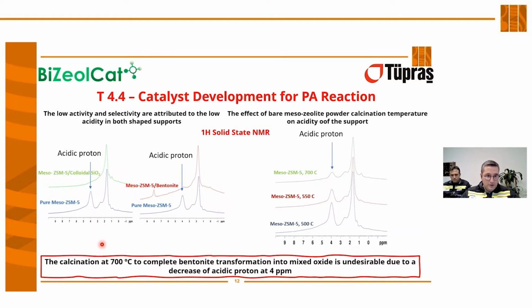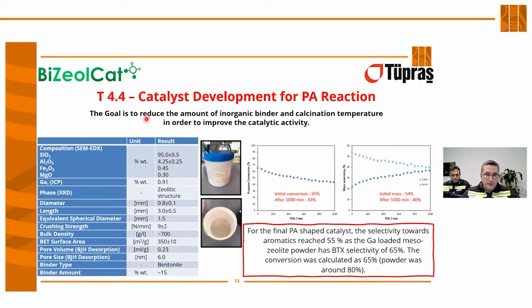Calcination at 700 centigrade degrees to complete the bentonite formation into the mixed oxide is undesirable due to the decrease of acidic proton, which reduces the catalytic activity. So we decided to reduce both the calcination temperature and the inorganic binder in order to increase the reaction performance.